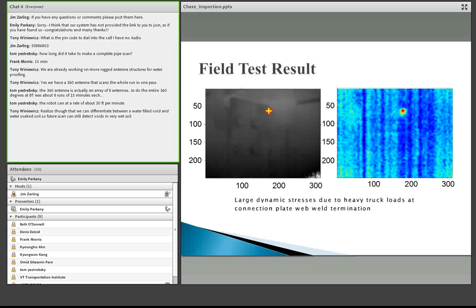And what you see here is the first ever image collected from a bridge with a fieldable thermoelastic stress analysis system, demonstrating that we are able to actually identify, detect, and quantify the stress concentration at a fatigue-prone detail due to random truck loading.